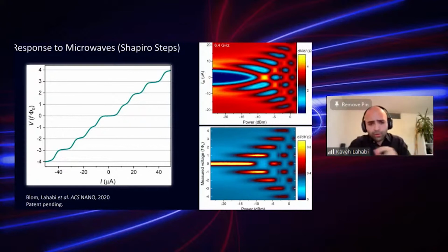Well, with Josephson junctions, of course, we always bias with a DC current, but in experiments with microwaves, you also have an AC component. So let me put it this way: every Josephson junction has two regimes. There is a static regime where, if you look at your washboard potential, your phase is trapped in one of the minima in your Josephson energy, and there you don't really have this AC component. There is no voltage. The voltage only occurs when your phase particle, let's say, on this washboard potential, starts to roll down. So below the critical current there is no voltage.